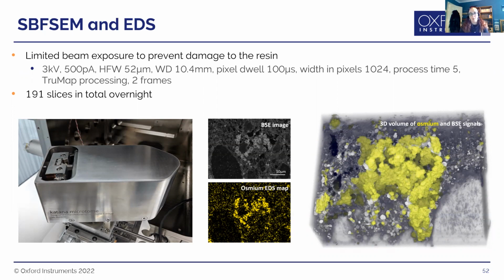Now, what can happen upon exposure to the electron beam is the resin softens slightly. So when you're trying to cut with your diamond knife, it can cause distortion in the surface because it's softened. A way to get around that is to have really low kV when you're doing it. And it becomes a bit of a challenge actually doing that and getting enough signal out of your sample. So often the samples are stained quite extensively. And in this case, this is some lamprey skin, and it had lots of osmium stain in it.